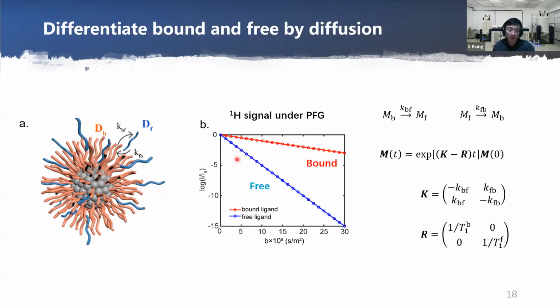So the bound ligands have much reduced diffusivity because it's a much larger particle in solution. The figure here shows the dephasing curves of the bound and the free ligands under the pulsed field gradient. The difference is big enough for us to separate their individual populations and to measure the exchange rate with this kind of exchange equation. Of course, the relaxation also needs to be considered during the NMR pulse sequence.